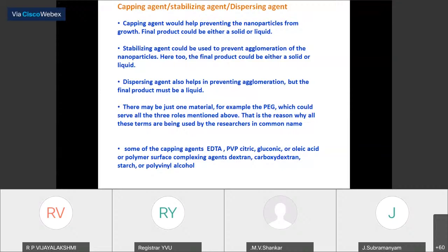So what is the action of the stabilizing agent? We can use PEG, polyethylene glycol, which can act as a capping agent, a stabilizing agent, and a dispersing agent also. In some organic materials, they act only for one particular purpose. So depending upon the material we are going to synthesize, we have to choose the capping agent and the stabilizing agent according to your requirement.